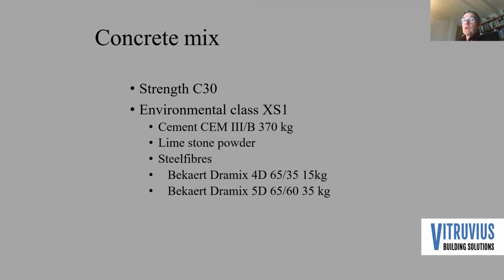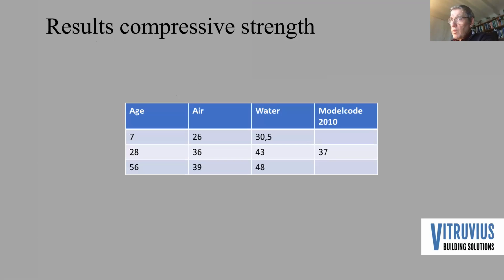The concrete mix was the following: strength C30, environmental class XS1. We used a lot of cement in it, 370 kilos, and that was because we had a lot of steel fibers in it. You can see it below, 50 kilos of steel fibers: long ones, 35 kilos, and very short ones, 15 kilos. The next slide, please.